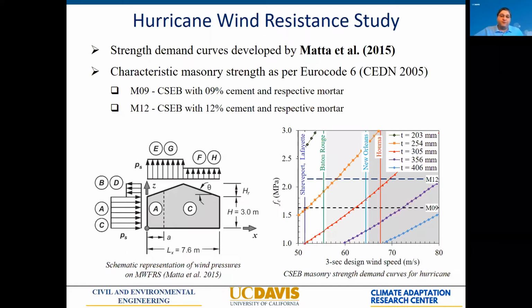And so when you find the intersection between one of these curves and the vertical line, as long as they are below the level given by the horizontal line, that is an optimal design for that type of structure. And what we found is that we can build walls that can take even Category 5 hurricanes in this place that is subject to very strong wind loads.